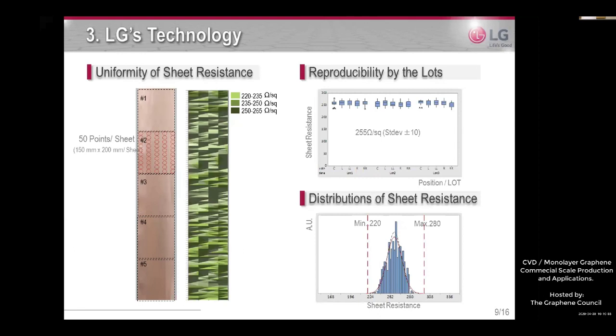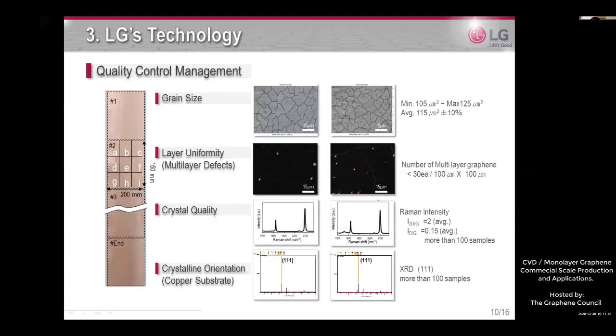Quality control is a very important key to secure the uniformity, reliability, and reproducibility. We evaluate the entire product. All graphene rolls were cut at this scale, and all the samples have been checked at least 50 points for sheet resistance evaluation. As a result, the sheet resistance value is about 255 with 10% standard deviation. The 10% standard deviation is LG's rule for quality control. So the distribution is very narrow. The grain size, layer uniformity, crystal quality, and crystal orientation of copper foil are also evaluated for quality control management.